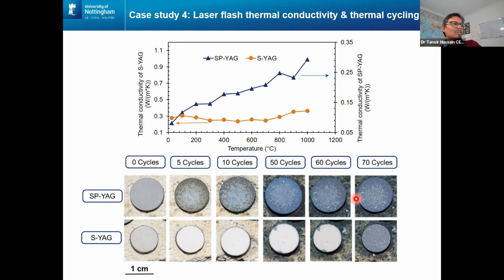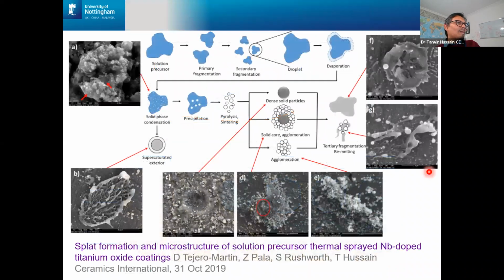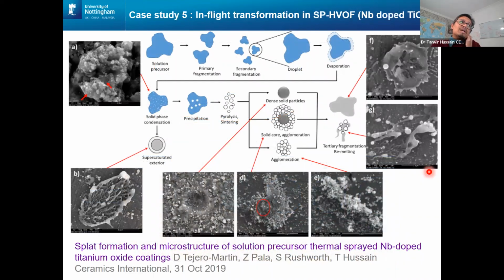However, when it comes to thermal cycling, our solution precursor system tends to fail much faster than the suspension one. So there is always a trade-off here between better thermal conductivity versus better lifetime. So what happens in a solution precursor? I was giving you an example of YAG.